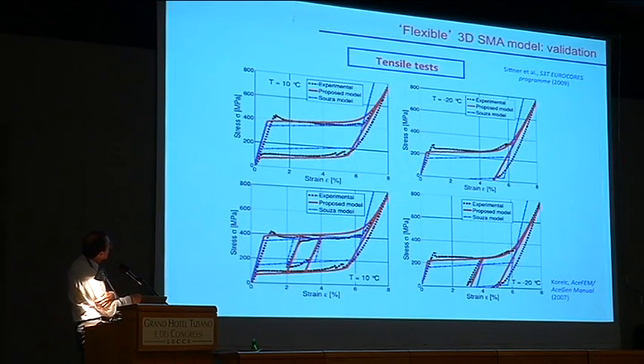Here you can see again the experimental data produced as the one I was showing you before. I forgot to mention that they were produced by Professor Sittner within a European project. And here you can see in black dotted the smooth curves, which are the experiments. You can see the original Souza model in blue, and you can see the new, proposed model. These are very simple tests because these are uniaxial tests, but clearly you can see that we get a much better fitting between the new model and experimental data. Souza is also doing a nice job, I think, but this new model is doing much better.